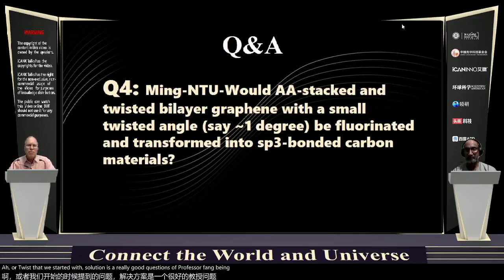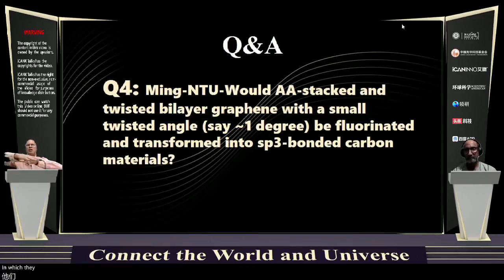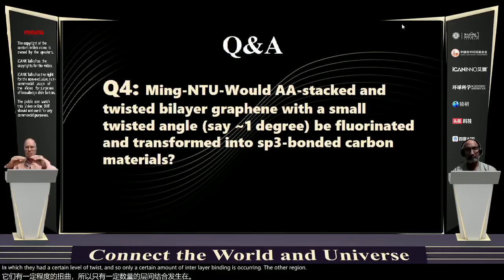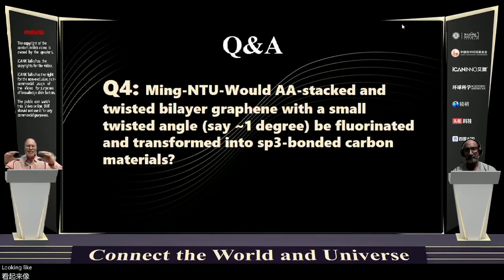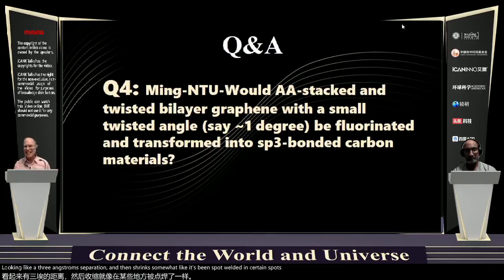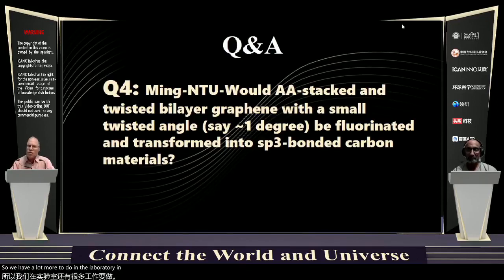Professor Feng Ding, before arriving at our center, I think published a paper in which they had a certain level of twist, and only a certain amount of interlayer bonding is occurring. In the other regions, it pops back out to looking like a 3 angstrom separation and then shrinks almost like it's been spot welded in certain spots. So interlayer bonding doesn't depend on perfect AB stacking, per calculations. We have a lot more to do in the laboratory in terms of looking at what sorts of interlayer twist angles can still lead to interlayer bonding forming based on fluorination or hydrogenation on the open surfaces.